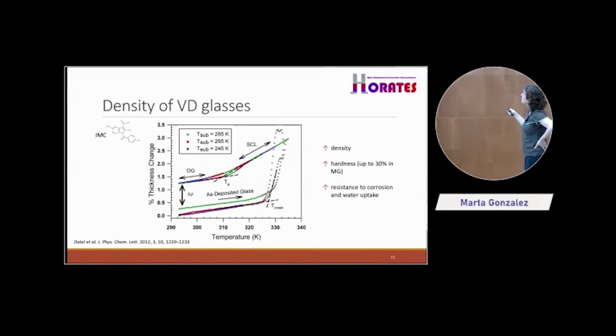The density is bigger, therefore the hardness is also much bigger. In metallic glasses prepared in this way, you can get up to a 30% more hardness in your glass, which is very important. And also, as I told you, the resistance to corrosion and water uptake is also related to density in part.